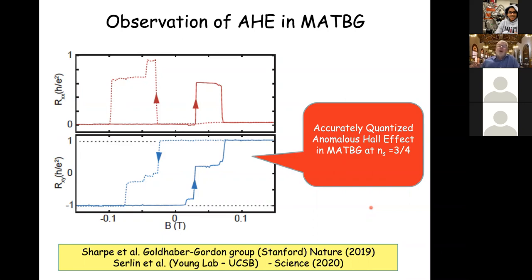And when you occupy the valleys differently, the cancellation that I referred to before that makes the Hall effect disappear cannot occur. So when we have insulating states at odd band filling factors, an odd number of Moiré bands completely filled, then we expect to see an anomalous Hall effect and a quantized anomalous Hall effect. And indeed, that is exactly what was seen very early on by the group of